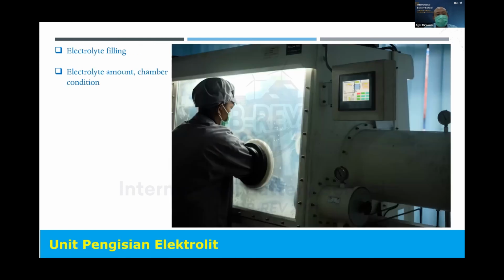After that, we move to the electrolyte filling. In the electrolyte filling, we must pay attention to the electrolyte amount and also the chamber condition. A chamber with no leak, with very low oxygen content and also very low moisture content will produce a battery with good characteristics. But we must also focus on the electrolyte amount. If we fill too much electrolyte, there will be some leaking of electrolyte after the final process, and it will affect the corrosion of the battery.